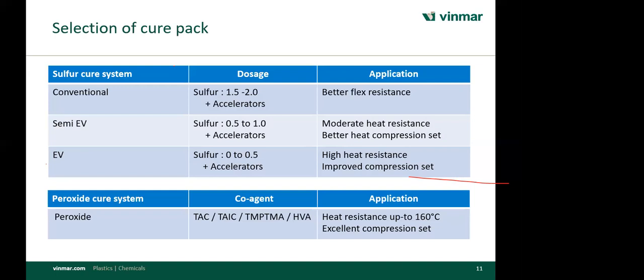So here I'll discuss a little bit on the cure packs. In EPDM, we recommend conventional, semi-EV, and efficient vulcanization. The dose of carbon black is very important. Sorry, the dose of the sulfur is very important. In the conventional system, the sulfur is 1.5 to 2.0, whereas in semi-EV it is 0.5 to 1, and in the EV system maximum 0.5 PHR of sulfur.